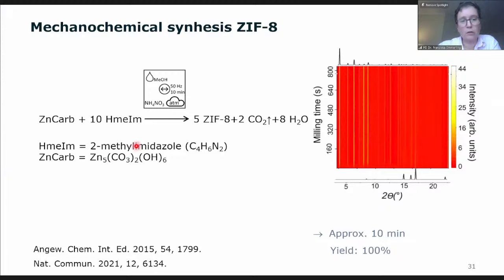So we use here basic zinc carbonate. That's a bit different from the recipe Yaghi and colleagues were using. They use the nitrate, but nevertheless, you get your pure compound, and you can also avoid to a great degree the use of any solvents. So that's fine. But then I had a new PhD student, and he was preparing samples to do some measurements.